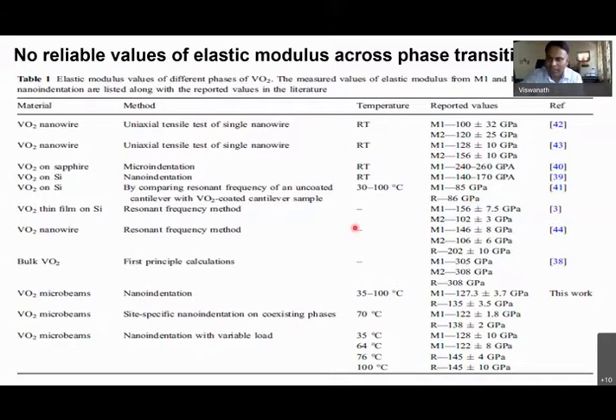So we thought about why there is a huge scatter, and whether we can use nano indentation, knowing where the phase transformation is happening. And we are able to find, I would say, more reliable results. We found around 17 gigapascal of change in the elastic modulus and 1 gigapascal of change in the hardness values. I will try to show this video.